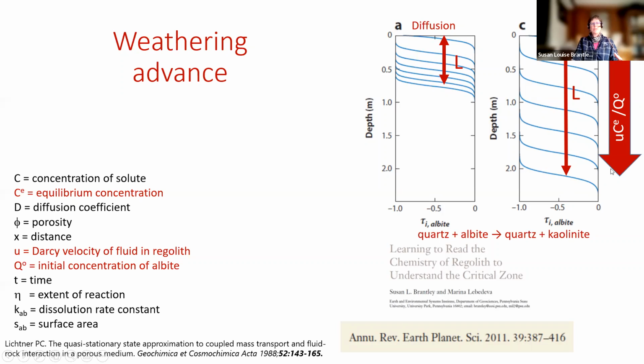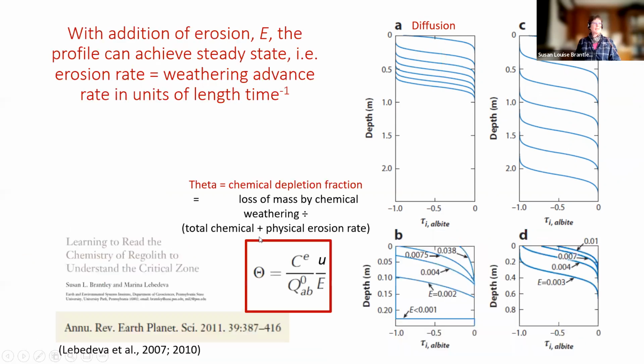The depth is telling you something about the solubility removal of material. And then this reaction front tells you about the ratio of transport and reaction. So that was all without erosion. That was a system where it was deepening with time. And I started out telling you that a lot of systems move to a steady state. So what if you run the models so you impose an erosion rate equal to this weathering advance rate, or this weathering advance rate here?